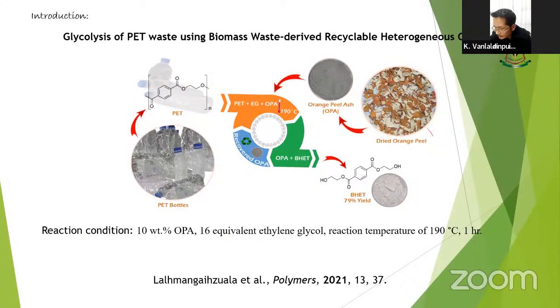So we collect the orange peel, we wash it thoroughly with water to remove all the contaminants and impurities, with distilled water. And after that, we dry it in sunlight or in a hot air oven. And after that, we burn it and we grind it to a fine powder and we sieve that one. Then we collect that ash. So we use this ash